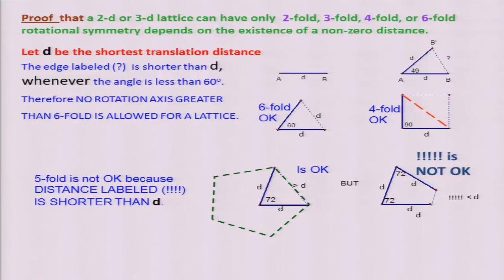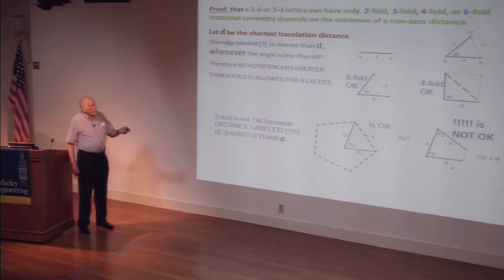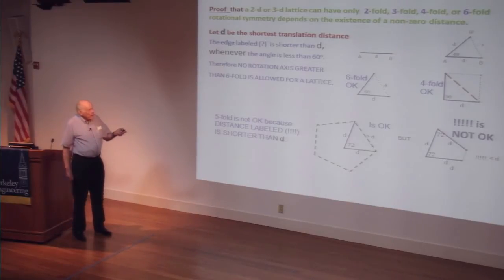Just to remind you, it's a very simple proof. I take a shortest distance from A to B, that's a D, and I take any angle less than 60 degrees. And I say, well, now, if this is a lattice point and this is a lattice point, that is a lattice point, then these two lattice points are closer together. And this has to be the shortest distance. If I can go through something like that, I can use then this distance to make still the shortest distance. Eventually, I have a continuum. So in order to have something with periodicity, or something that is not a continuum, there has to be a shortest distance and nothing shorter.